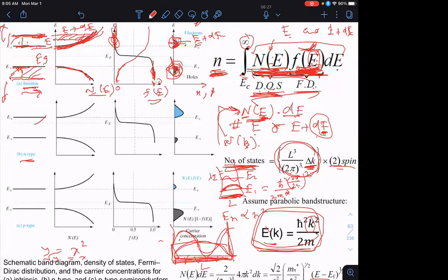And what you'll see is the main difference will be the Fermi level, which was sort of in the middle of the gap in the intrinsic case, moves up close to the conduction band, and that will lead to a larger number of majority carrier electrons and a corresponding decrease of the minority carrier holes compared to the intrinsic undoped case. In the intrinsic case, the number of electrons has to be equal to the number of holes.